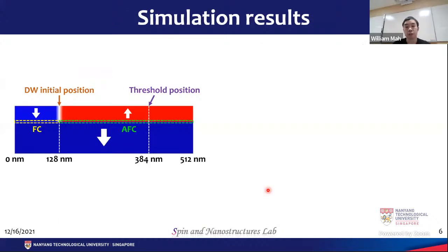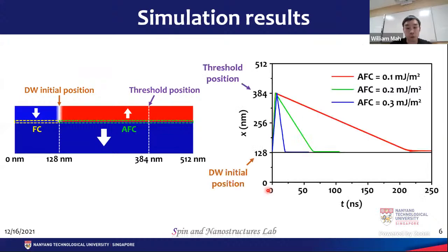We did some simulations to see whether we can achieve the integrate and leakage functions. The graph on the right is a domain wall position against time graph. This 128 nanometer corresponds to the initial position of the domain wall, which is this point on the drawing. 384 nanometers is the threshold position, corresponding to this point on the drawing.